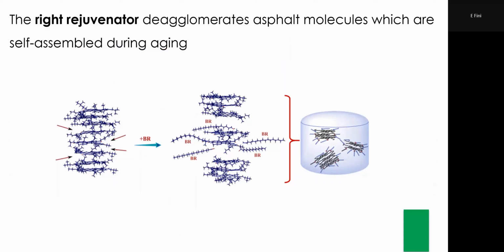So aggregated asphaltenes need to be broken apart to get the conformation of the unaged status. In the unaged status, we don't have such large agglomerates because they're not as polar to attract each other. In this case, the rejuvenator's role is to get into those stacks and break them into smaller ones. I put this in a schematic to give you an idea of what's happening when you do true rejuvenation. If you just add a bunch of liquids around this stack, the one on the left, you will get softer material, but you have a bunch of small molecules and you still have the same agglomerates sitting there, nothing changed. That still softens your material, so you get lower modulus, but you don't really recover the properties, you don't revitalize it.